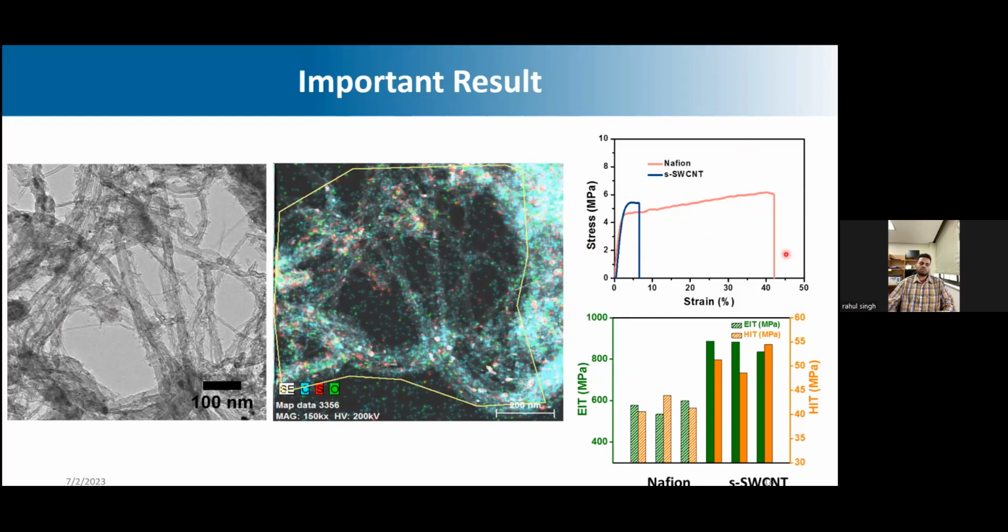They are flexible membranes, but after introduction of the single wall carbon nanotubes, it became a little brittle and the flexibility was lost. We need to consider this, because we cannot introduce as much as we want, since they damage the polymer structure.